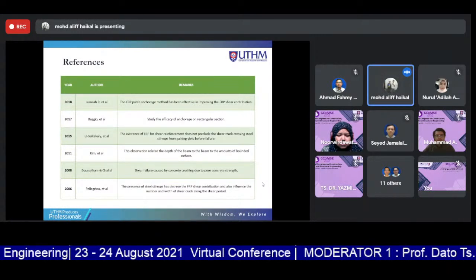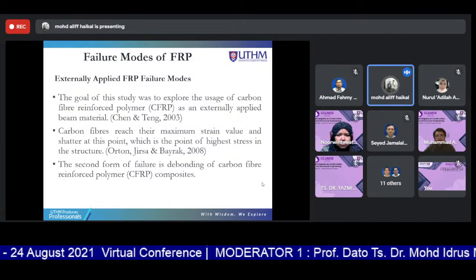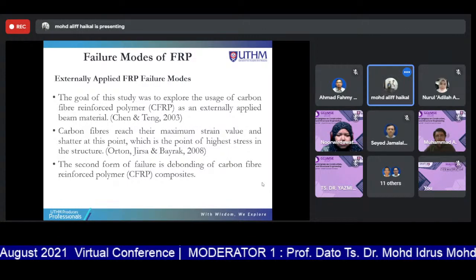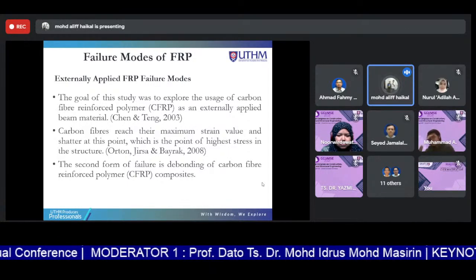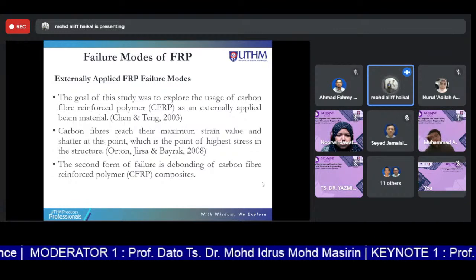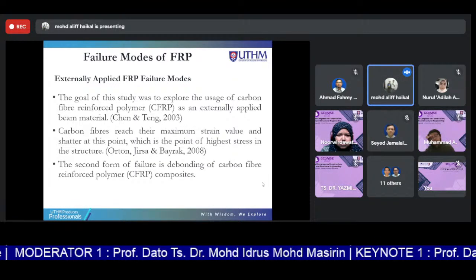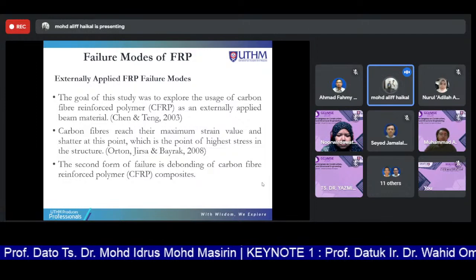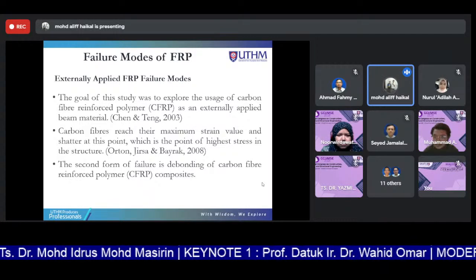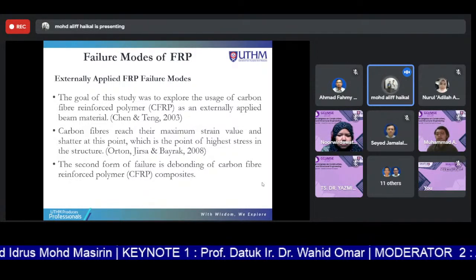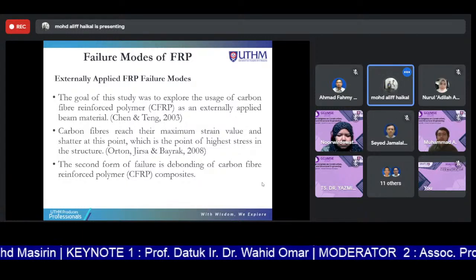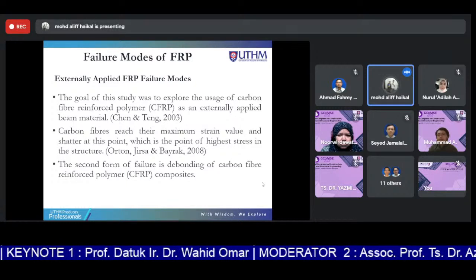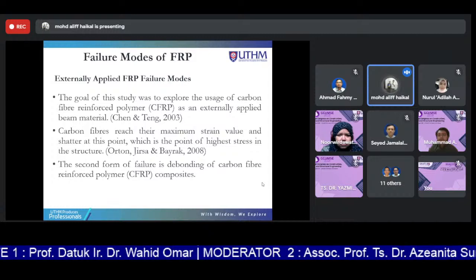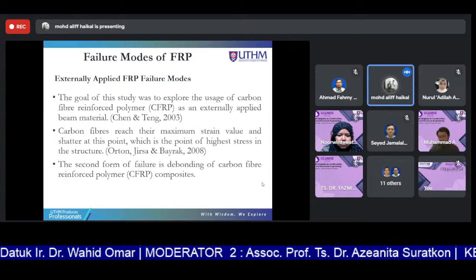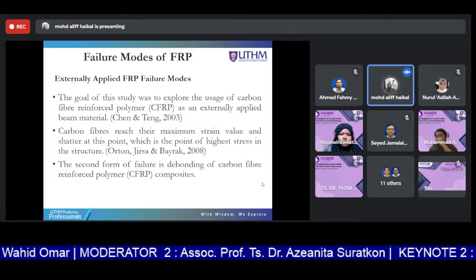we use. And let's go to the failure modes of FRP. Externally applied FRP failure mode. The goal of this study was to explore the uses of carbon fiber reinforced polymer (CFRP) as an externally applied beam material. Carbon fibers reach their maximum strain value and shatter at this point, which is the point of highest stress in the structure. The second form of failure is the debonding of carbon fiber reinforced polymer (CFRP).